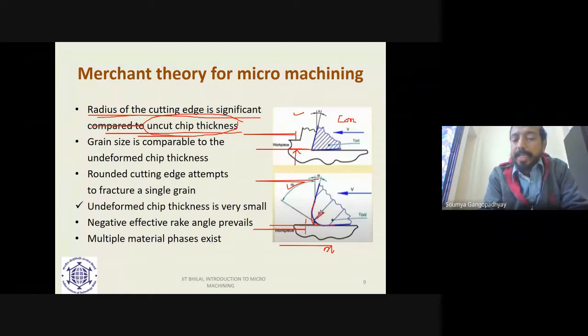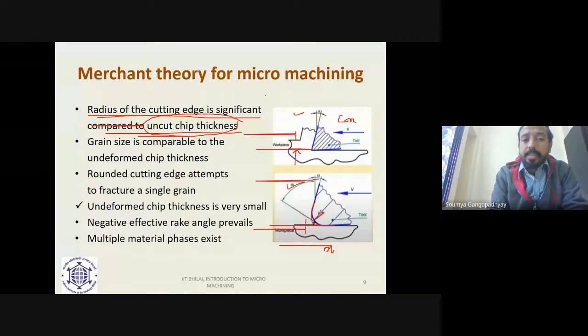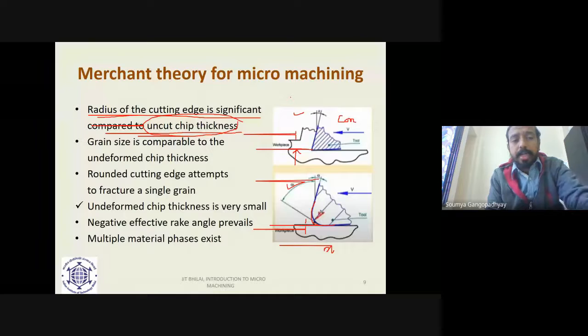And when it acts like a blunted cutting, the rubbing and plowing become very, very significant, and then shearing becomes insignificant. Until and unless shear deformation takes place, you will not have chip formation, even in the micro cutting regime. And that makes it a very, very complex affair. And that is what is called the size effect. Okay, this is about the cutting edge and the uncut chip thickness.